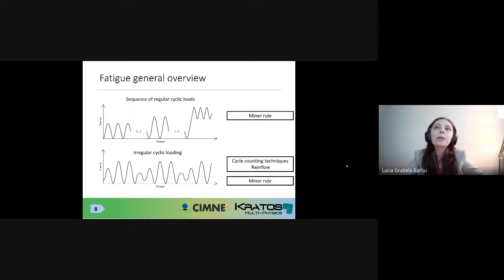And here, for instance, you need a rule which helps you sum the effects, the damage effects, of each one of these blocks. The most widely used is the Miner rule with linear damage accumulation. But also you can be dealing with irregular cyclic loading. In these cases, you need to use a cycle counting technique, such as rainflow, I would say the most famous one. After you divide this irregular cyclic load into cycles with similar characteristics, you group them and apply them in a specific order, then you can apply the Miner rule.